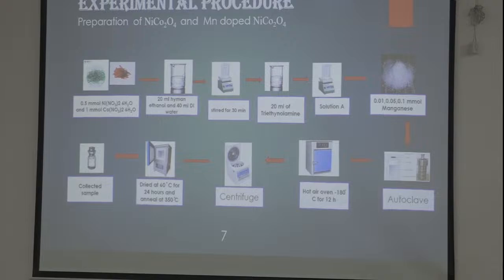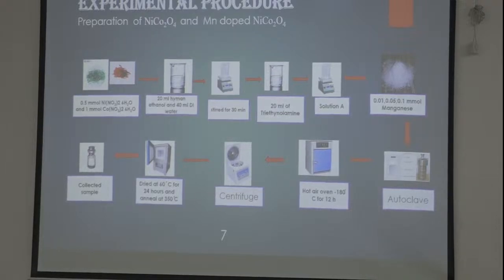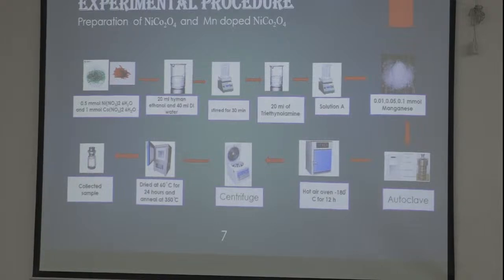This is the experimental procedure for the preparation of nickel cobalt oxide and manganese doped nickel cobalt oxide with different ratios. I used the hydrothermal method to prepare nickel cobalt oxide and manganese doped nickel cobalt oxide. In this, I used triethanolamine as a structural directing agent, which also helps give a multi-dimensional morphology.